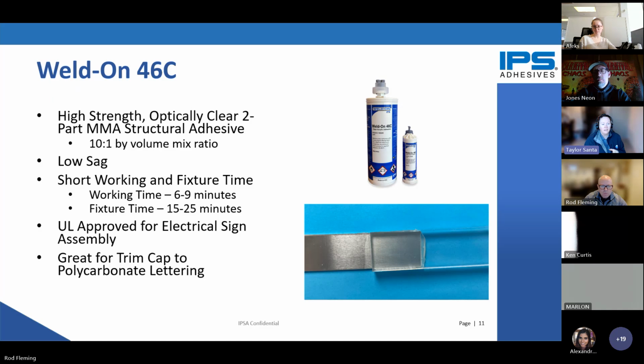Again, low sag. It does have a shorter working time, about 6 to 9 minutes, with a fixture time being 15 to 25 minutes. So you have to be a little bit cautious when you're using this product, just to make sure all your parts are laid and in the right configuration before it really kicks. And again, we know this is going to be used in electrical sign assembly, so we have it UL approved. And this is really great for trim cap and polycarbonate lettering. Yeah, it's a great product.